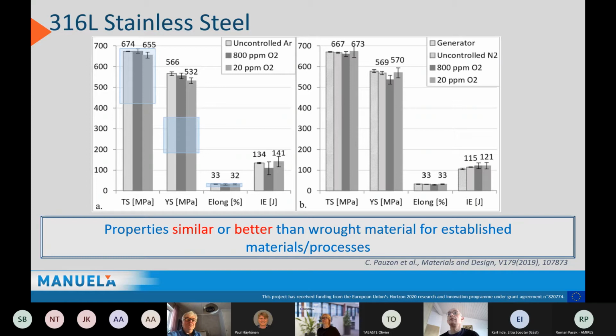But what you see here is that we get very, very good properties. We have ultimate tensile strength in the range of 650, 670 in basically all cases, right? Which is similar to or better than any wrought material from the established material processes. If we would take conventional stainless steel, manufacture it in other ways and machine it out, you won't reach these properties. And that's because of the unique microstructure you create during the additive manufacturing process. Next slide, please.